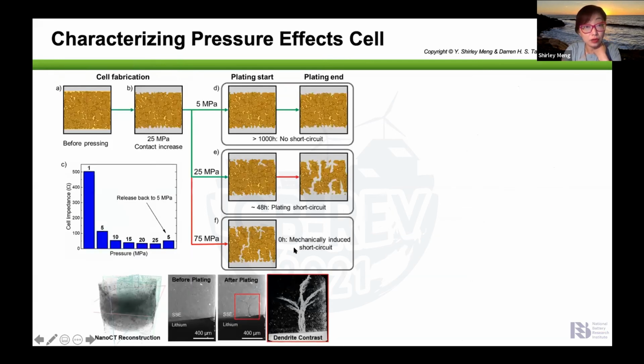On the negative electrode side, in the early days when people tried to cycle the batteries at high pressure, they always met the challenge of short circuit. And if you do a CT scan of the solid-state battery, you can see these tree-like dendrite features.